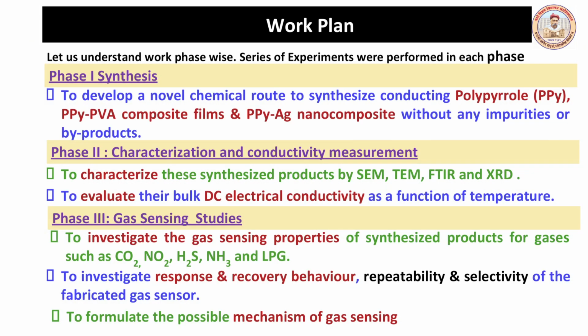In phase 1, the synthesis was done in detail to develop a novel chemical route to synthesize conducting polypyrrole, polypyrrole polyvinyl alcohol composite films and polypyrrole silver nanocomposite without any impurity or byproduct. In phase 2, whatever samples we have prepared, their characterization is essential to know about their purity. So we have done SEM, TEM, FTIR and XRD of the samples, as well as, if they are conducting polymers, then we need to check their DC electrical conductivity. So we have checked DC electrical conductivity as a function of temperature.